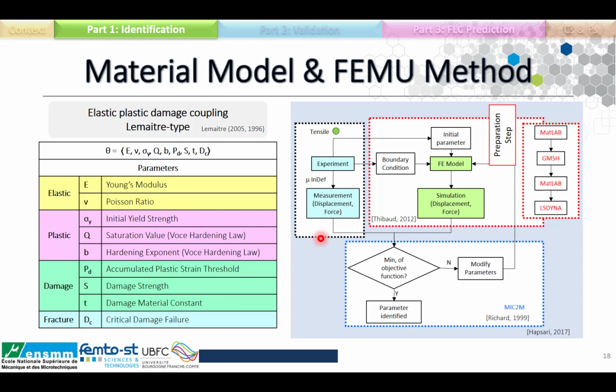So the idea is quite simple, on paper at least. We have on one side an experimental test, the micro-in-depth test. We have on the other side a numerical simulation of this test using the elastoplastic damage coupling Lemaitre type model. And we use a minimization toolbox in order to minimize the difference between the experimental forming force and the numerical forming force. When this difference is minimized, theoretically we obtain the material parameters.